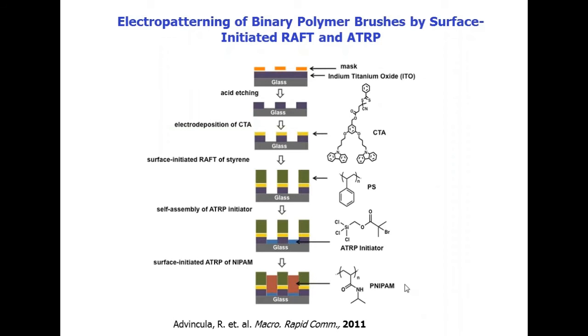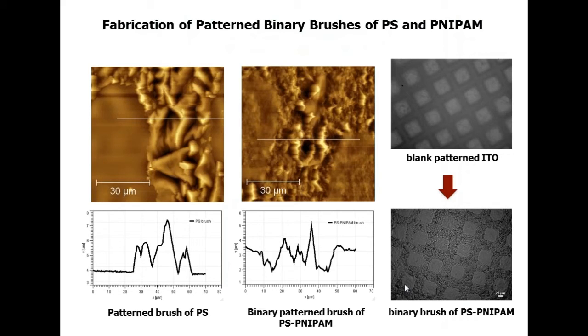So the question is, what is the utility of surface chemistry and surface functionalization analytical methods here? As shown here, an AFM image that differentiates the surface with the polystyrene polymerized on the ridges. However, after grafting the PNIPAM, we can clearly see here a difference in morphology by AFM. It's even more dramatic when we see a larger scale. So AFM does not give that information to us. SEM does not give this information to us. So in fact, we only know it's polystyrene and PNIPAM just because I said so.